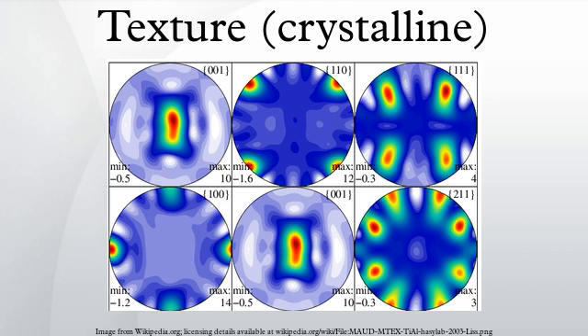The degree of texture is often subjected to an evolution during thin film growth, and the most pronounced textures are only obtained after the layer has achieved a certain thickness. Thin film growers thus require information about the texture profile or the texture gradient in order to optimize the deposition process.